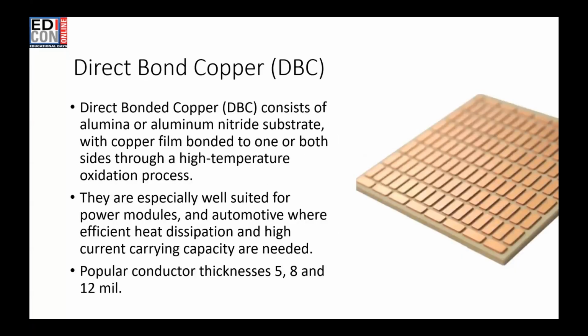The direct bond copper, DBC, consists of an alumina or aluminum nitride substrate with copper films bonded to one or both sides through a high temperature oxidation process. So basically, you have a copper film which is bonded to, say, an alumina substrate, and that bonding takes place at in excess of 1000 degrees C, and that forms an oxide layer between the two. And that's how that works. DBC is especially well suited for high power modules and automotive applications, where efficient heat dissipation is provided and high current capacities are needed. In terms of the popular conductor thicknesses, they range from 5, 8, and 12 mil.